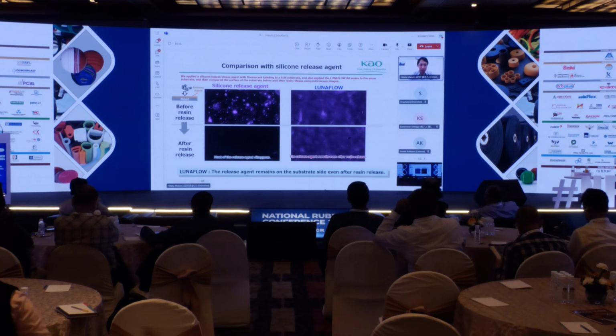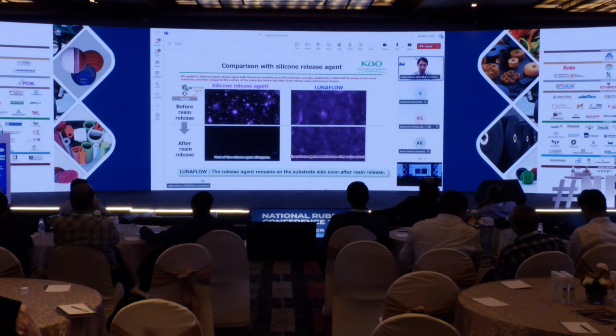Before resin release, the silicone release agent is here. However, after resin release, most of this agent disappears like this. On the other hand, LUNAFLOW can keep the surface of the substrate. LUNAFLOW remains on the substrate side even after resin release like this.